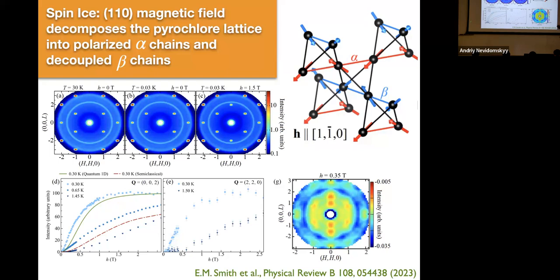Those will all get polarized to the extent possible. So the spins will all cant along the spin direction, along the field direction, and it will decouple the beta chains. Okay, so it polarizes the alpha chains and it decouples the beta chains.